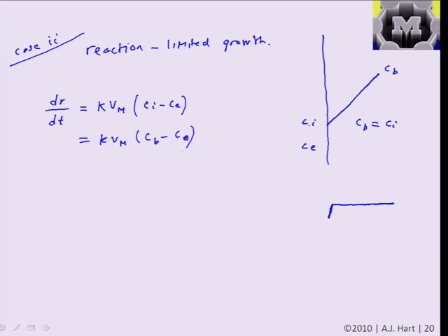So now if we assume, again, that the concentration difference at the interface, the important concentration difference, is independent of the particle size, now it's saying that the rate of change in the radius is the same for all particles, which would mean that a 5 nanometer particle, say in 1 minute, becomes 6 nanometers, and a 10 nanometer particle at 1 minute becomes 11 nanometers. So we're certainly not focusing the distribution.